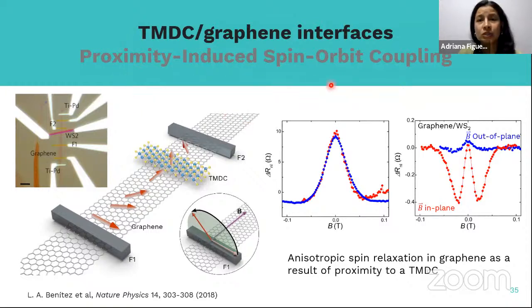I mean, this proximity-induced spin-orbit coupling in graphene. What has been observed is that if you transfer a TMDC material on top of graphene and then study the spin transport in this system, you have an anisotropic spin relaxation in graphene as a result of proximity to the TMDC. So if you study the spin transport with one orientation of the magnetic field, and then with the perpendicular orientation, you see different results for the transport of that spin current. That is a consequence of the spin-orbit coupling induced in graphene because of the interface with a TMDC, a large spin-orbit coupling material.